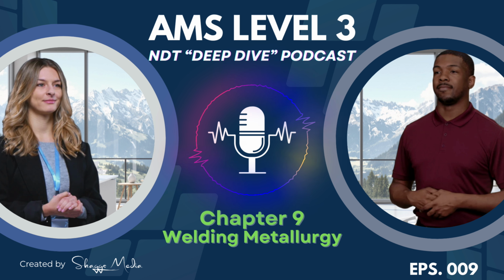So, if you accidentally form martensite, or maybe you deliberately quench a part to make it super hard, like for a tool, you've got this brittle structure. How do you fix it? Well, that's tempering, right? Correct. Tempering is the crucial follow-up step after quenching. You take the hardened part, the martensitic part, and you reheat it, but this is critical. You keep it below that A1 transformation temperature, 1333 degrees.